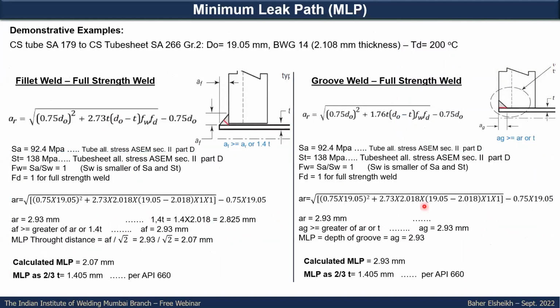We will assume here an example just for illustration. A tube of carbon steel, SA-179, welded to a tube sheet SA-266 Grade 2, all carbon steel. Tube diameter is 3/4 inch, and BWG 14, which is 2.108 mm. Design temperature is 200 degrees Celsius. We assume this to build these two examples, one for fillet weld and one for groove weld. The same equation, if you can remember from UW-20, here we will use for calculating how much a_r is required. And from the a_r we calculated, we get the allowable stress from Section II Part D for the tube and for the tube sheet, and then get f_w and f_d, which will be used in this equation. And here, if you can see the a_r calculated, the result is 2.93 against the tube thickness 2.108. So it is higher than the tube thickness.